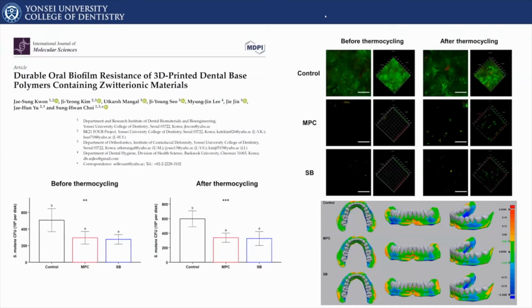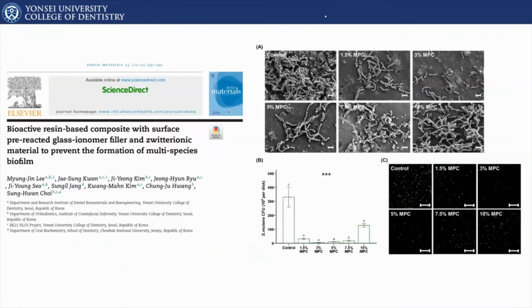So this is different to just surface coating, I think, because surface coating may have some aging effect, but because this is incorporated into the polymer itself, the effect is much more durable, and it did not have any negative effects on accuracy or physical properties or other mechanical properties, as we investigated. But our interest went further when we carried out these experiments that were published in 2019.